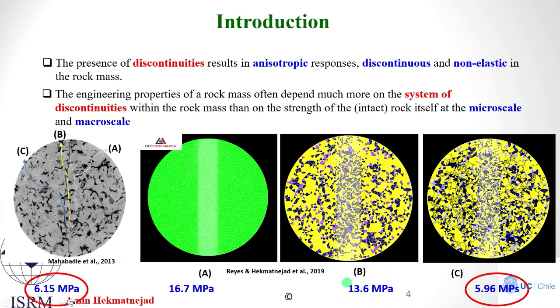In experiment B, or the second experiment, image processing techniques were used to capture the heterogeneity of the rock material, here the minerals, and incorporate it into numerical modeling, which improved the numerical results compared to the laboratory observation. As you can see, here the result is 13.6 megapascal, which is closer to the experimental results. However, it's far from the reality.